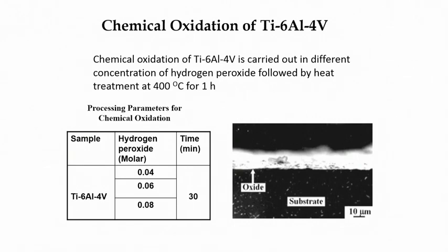Here, chemical oxidation of Ti64 substrate was carried out in different concentrations of hydrogen peroxide solution, followed by heat treatment at 400 degrees Celsius for 1 hour. The basic purpose of this oxidation treatment was to make the Ti64 bioactive.